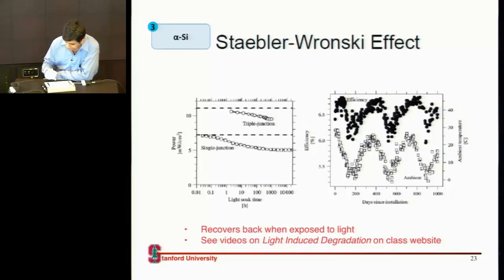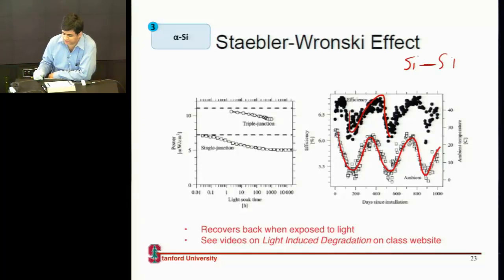So this cell, let's say you took it and you placed it in Arizona sun, which is as good as placing it in an oven. If you've been to Arizona in summer, or South Texas, it's just like being in an oven. So if you look at the efficiency, during the summer it goes up, and during the winter it comes down. Because during the summer you're annealing the defects in the cell out, because when you keep it exposed to light, these bonds reform and your efficiency goes back up. And so it's very interesting, the temperature dependence of these cells.